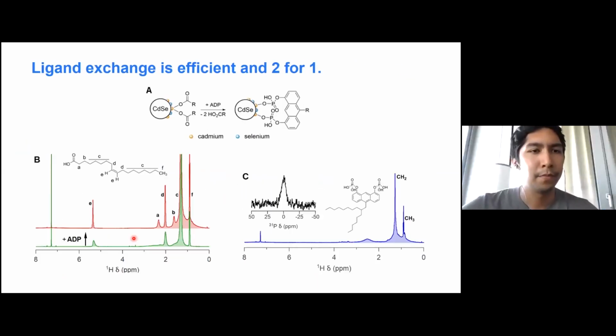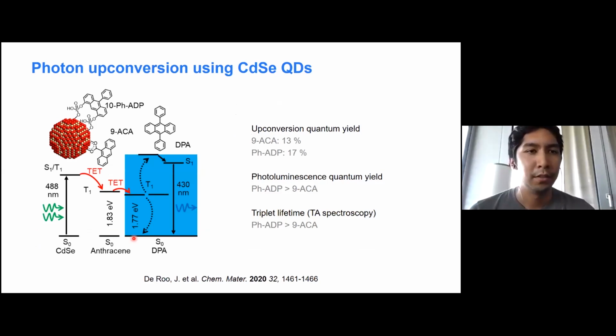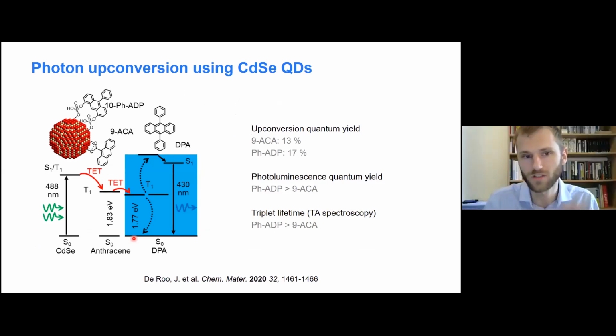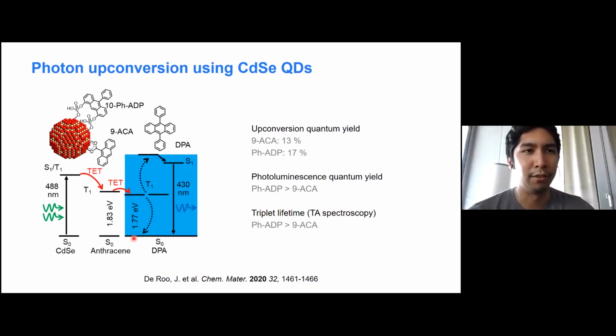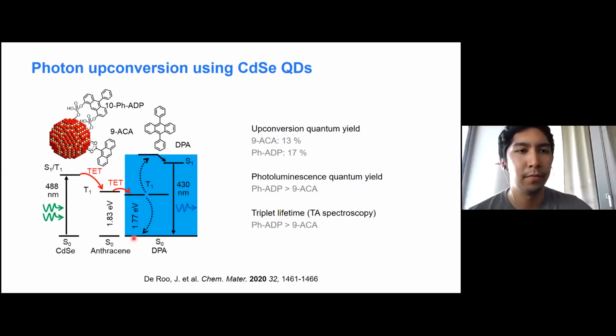Yes. So basically, all the measurements were done at the concentration that gave the optimum quantum yield. There was a series of different concentrations, then the quantum yield was determined, and then we did everything with the sample that gave the highest. Okay, and do you know what ligand coverage that was? Very low. It was only a few per nanocrystal. I think maybe even 2. Okay. Cool. Thanks.